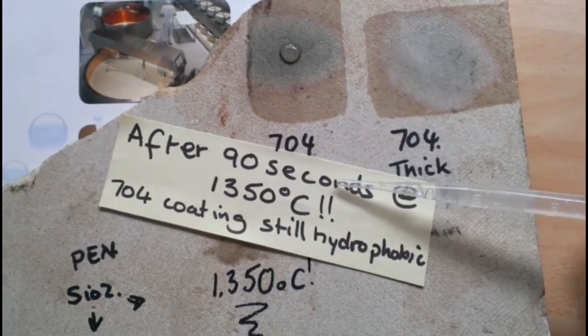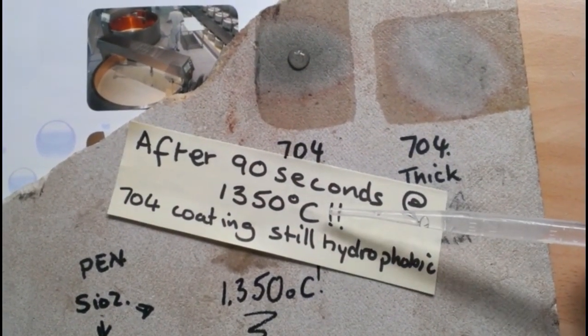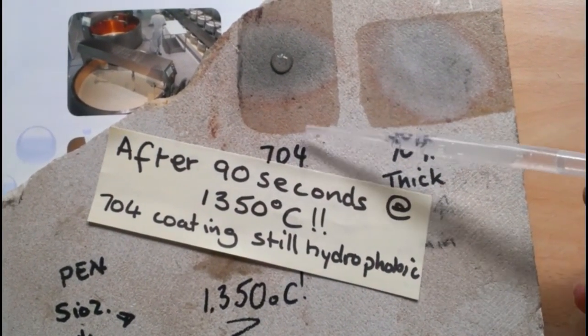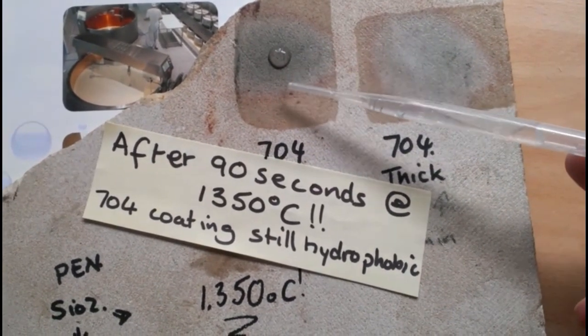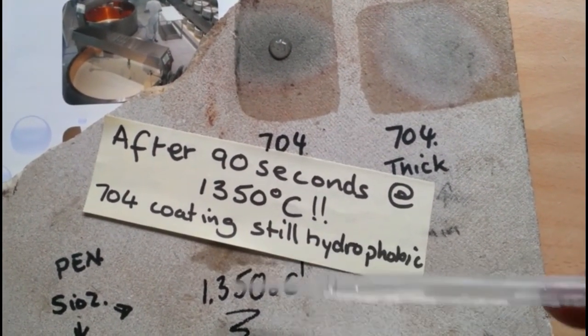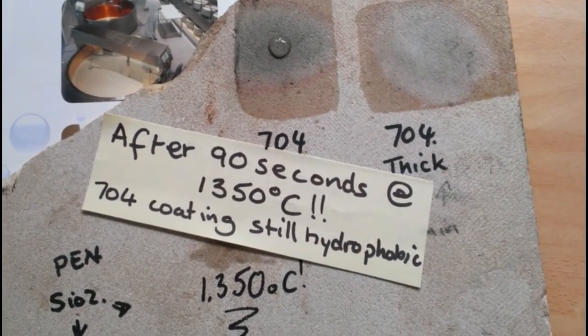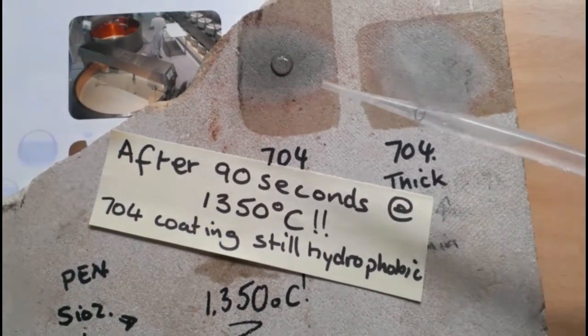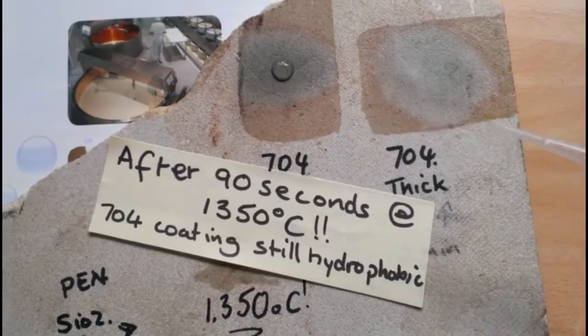After 90 seconds at 1350 degrees, the 704 coating is still working perfectly well, and here is the standard stone which of course is absorbing. So massive heat resistance and heat tolerance from the 704 coating.